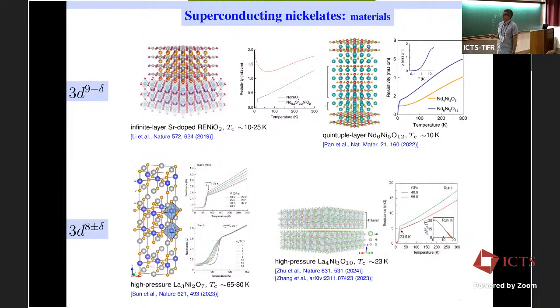These are bilayer systems, lanthanum 3 nickel 2 oxygen 7, superconducting even without doping, and also these 4-3-10 compounds with similar structuring also under high pressure, but now with 3 nickel layers, whereas you have two nickel layers here. That was just published in Nature this year, but it was already reported on the arXiv last year in fall.